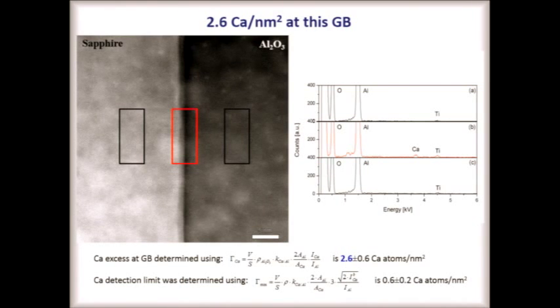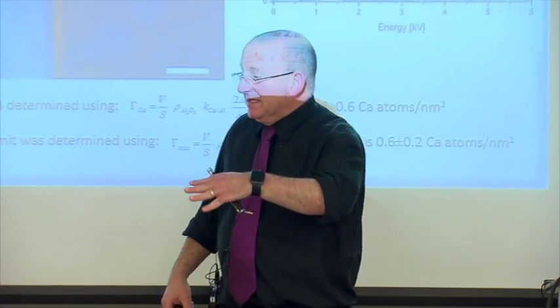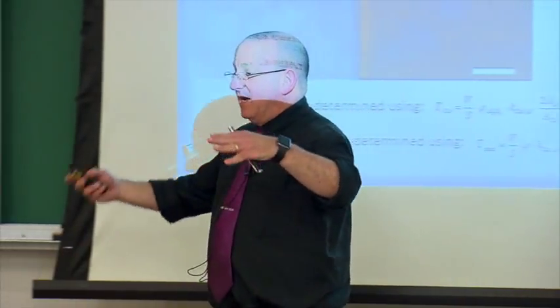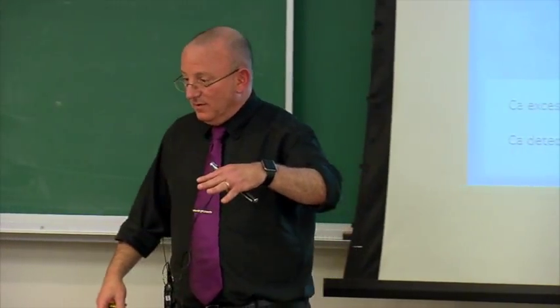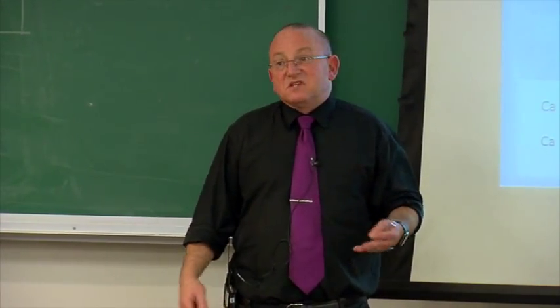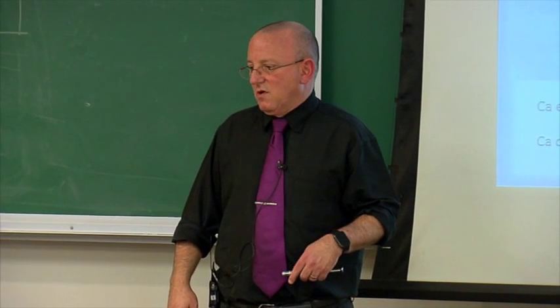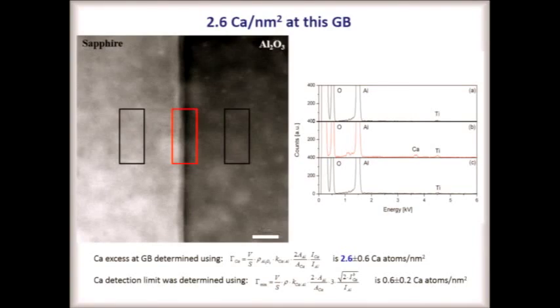So this is the basal plane of alumina. There are about 10 aluminiums per nanometer squared on the basal plane. Let's assume that the calcium is replacing the aluminum for the moment. So this is about a quarter of a monolayer. A quarter of a monolayer of calcium at this basal plane, causing this increase in grain growth. By the way, to think that it's all in one plane is way, way oversimplistic, and I'm not saying that.